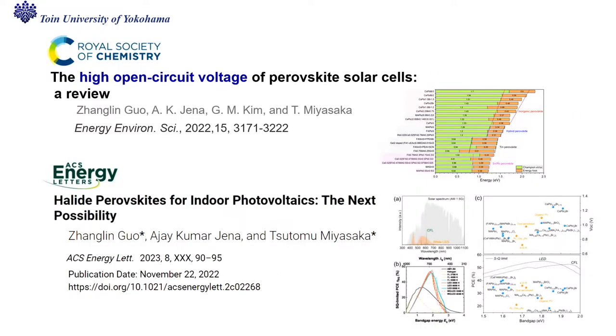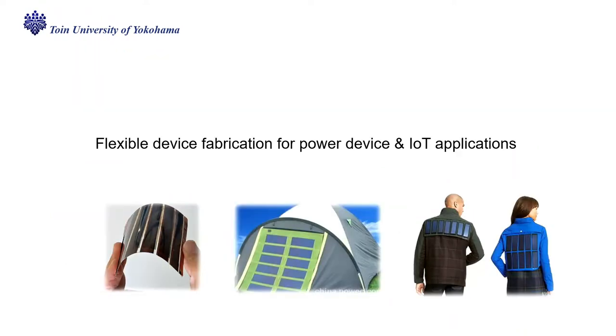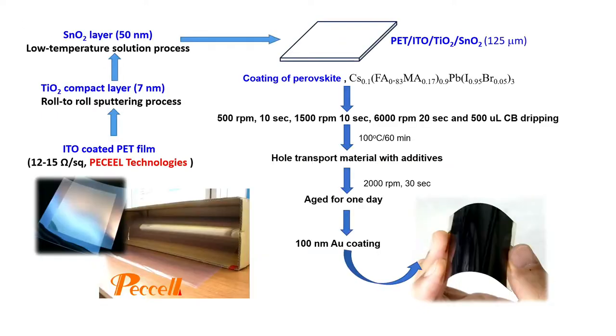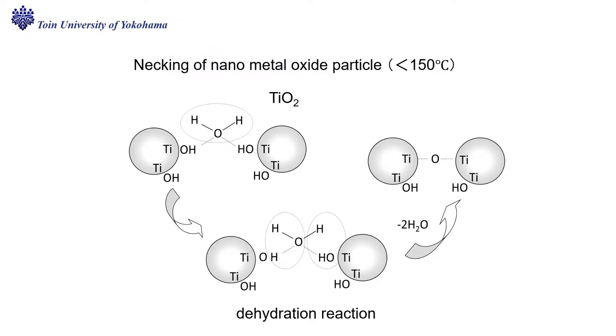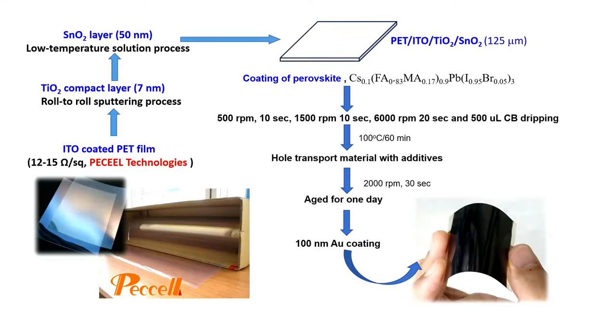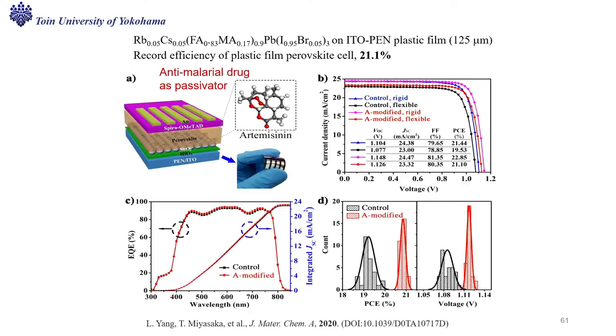So based on this result, we are now working on indoor application of perovskite in addition to outdoor application. But we have to establish the low temperature process. For example, the TiO2 or tin oxide, we have to make at relatively low temperature. This is by using a dehydration reaction, same as cement making. So we are using a plastic film. My company, Peccell, is now supplying the plastic film with very low surface resistance, 12 to 15 ohm per square. So our top efficiency was 21% for the plastic-based flexible perovskite solar cell, passivated by artemisinin. This is an anti-malarial drug.